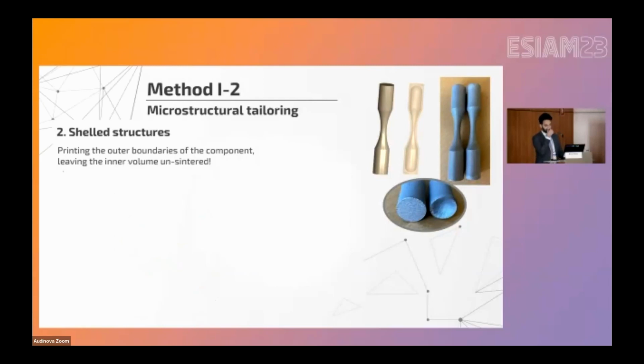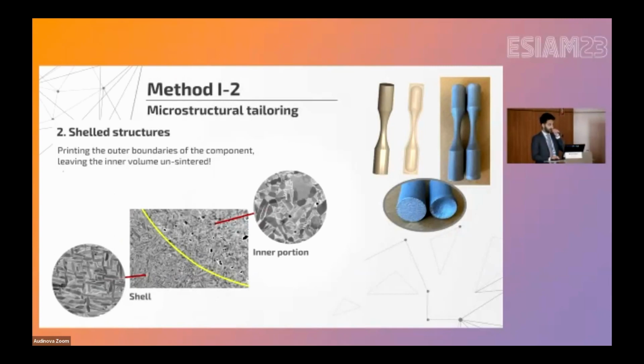So we checked this. We had shell structure, typical specimens for fatigue testing. You can see one of them was printed solid, the other one was shelled. They were both exposed to HIP, standard HIP, we didn't change it. The standard HIP that we use for titanium, same parameters. You can see also there is some shrinkage on the shell sample. Then we did microstructural evaluation.